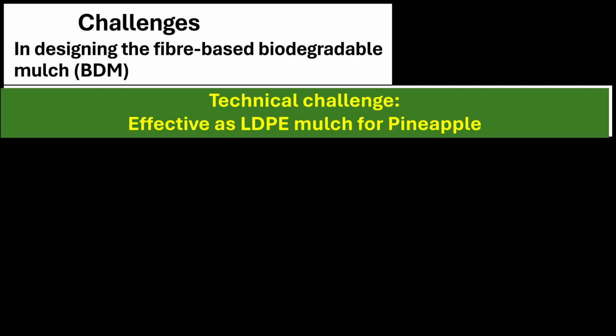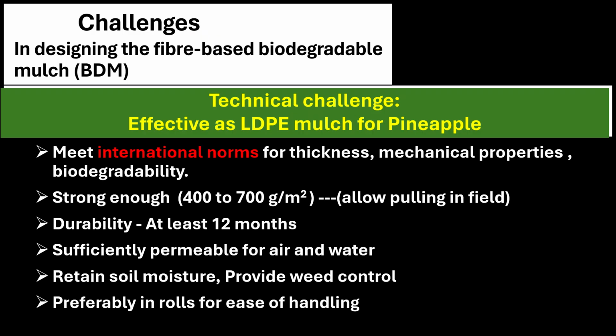So we knew that the banana fiber based mat that we were going to fabricate was not going to be as strong and as durable as the low density polyethylene film, but we had to ensure that it meets the international norms in terms of thickness, in terms of mechanical properties. So by thickness, it should be around 400 to 700 gram per meter square. Why? Because these mats were going to be pulled in the field for plantation. So if it is weak, it's going to break in the field.